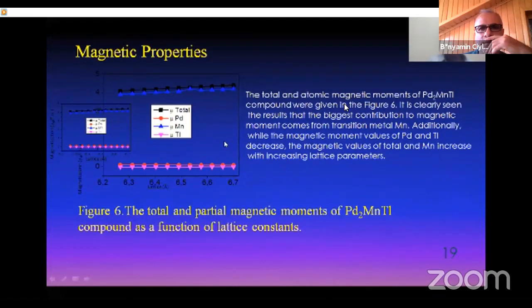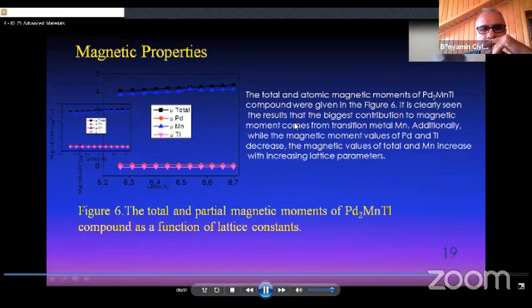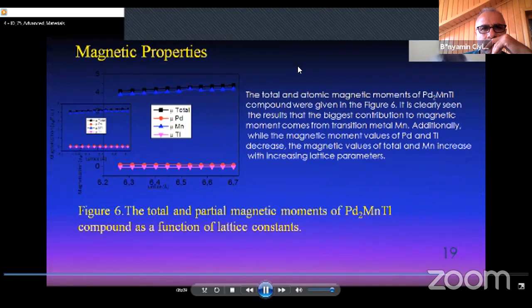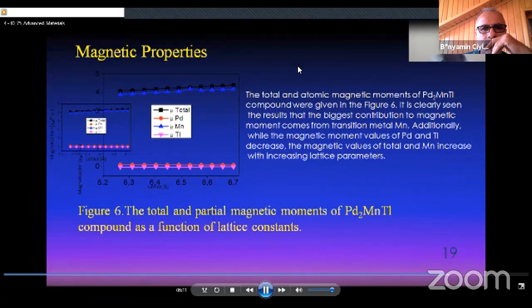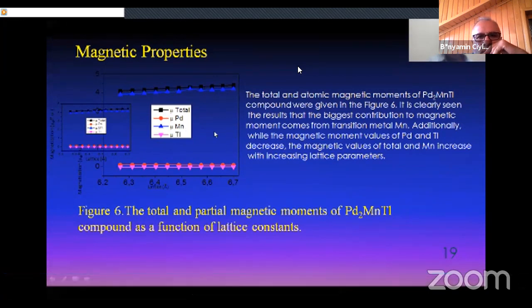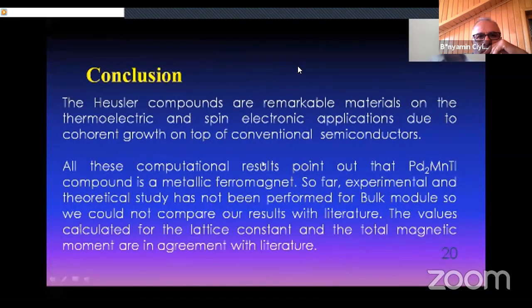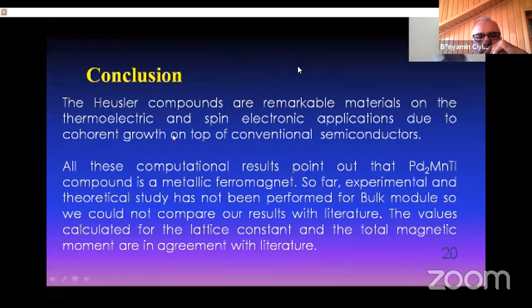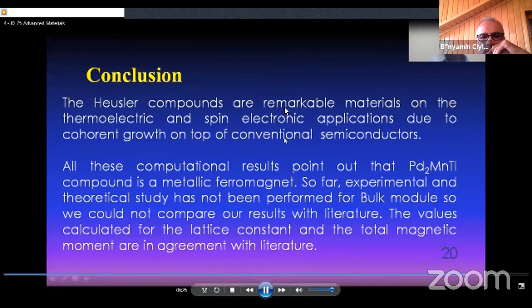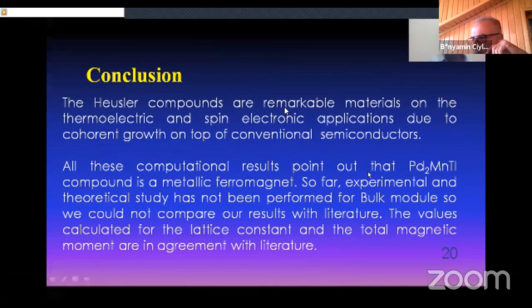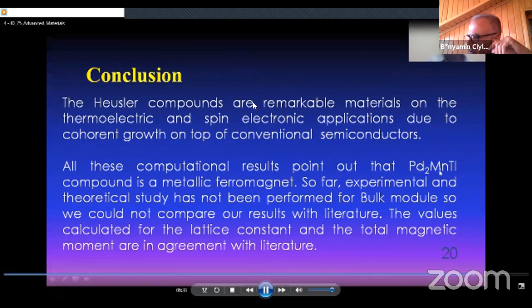The total and atomic magnetic moments of this compound are given in Figure 6. It is clearly seen from the result that the biggest contribution to the magnetic moment came from the metal manganese. The Heusler compounds are remarkable materials for thermoelectric and electronic applications due to coherent growth on top of conventional semiconductors. All these computational results point out that the palladium two manganese thallium compound is a metallic ferromagnet.